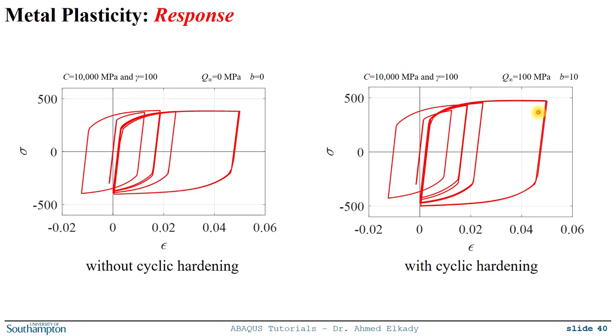This is the final slide that shows some examples here. So this is some hysteretic behavior where I'm using a value of C of 10,000 megapascal and gamma 100, and I'm not using any cyclic hardening. So that's why you don't see any change in the size of the yield surface. So I put Q infinity and B equal to zero. So this is how it looks.